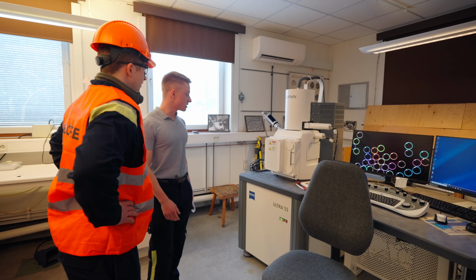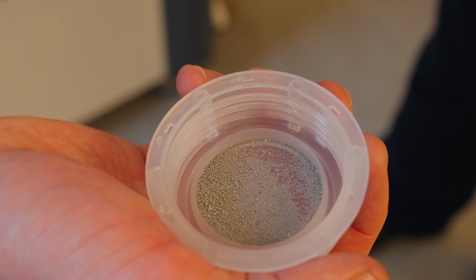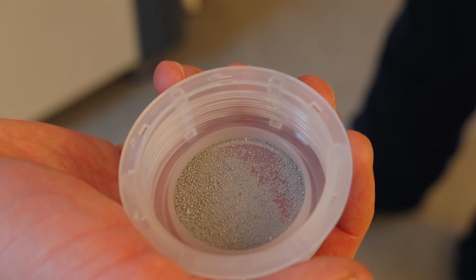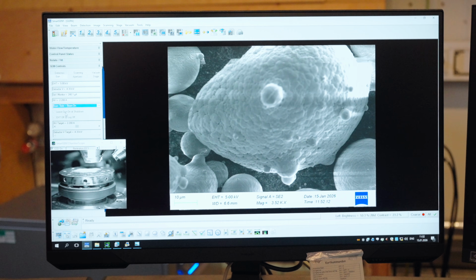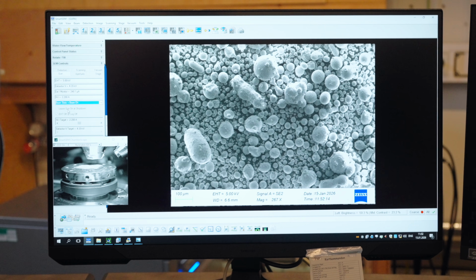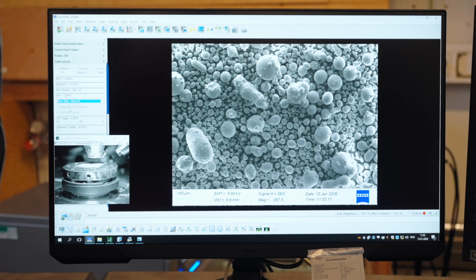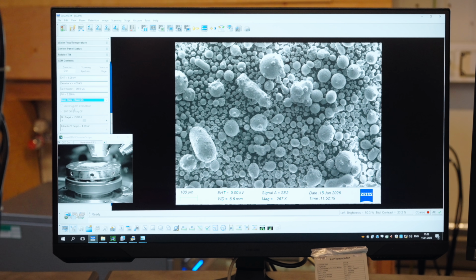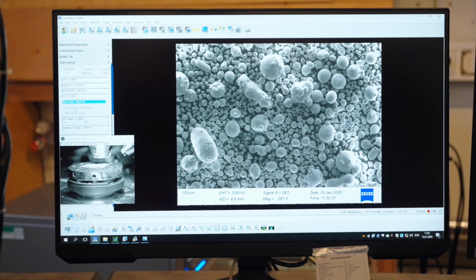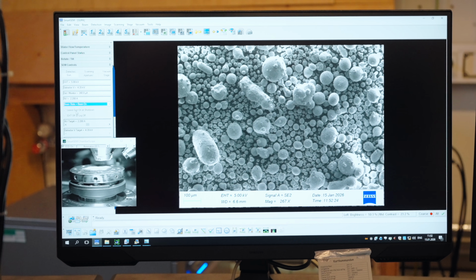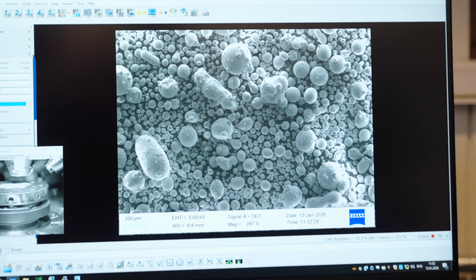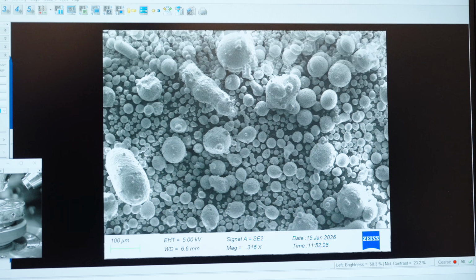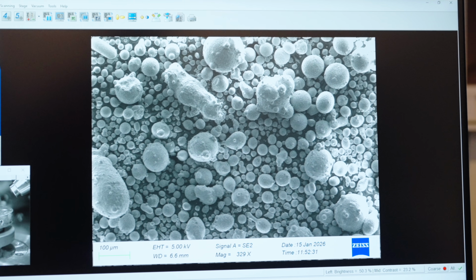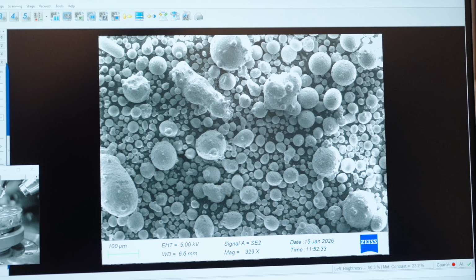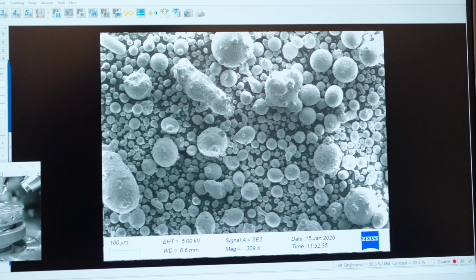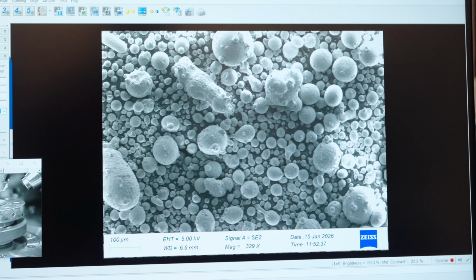So here we have it. This is our scanning electron microscope. This is a piece that I've prepared. It's a powder, so we placed it in a holder in here. What? So this is a big thing, because usually when using light optical microscopes, you're limited to about 1,000 times magnification because light becomes too big. So instead you need to use electrons to actually get a higher magnification. So you're blasting electrons at it, and then effectively looking at what reflects back. Yes. But light would be too big. Light would be too big.